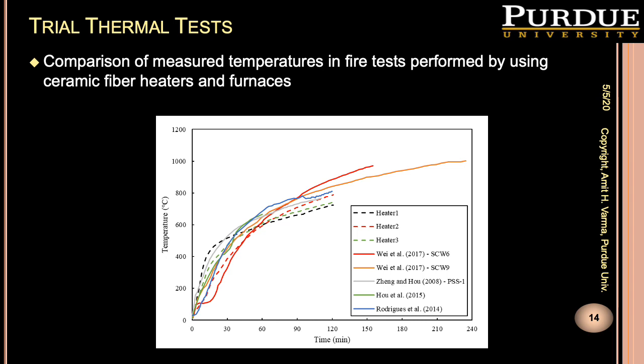I've also added a few lines from furnace tests conducted and available in the literature by different researchers. What all these plots show is that the typical temperature versus time curve that we obtain by using the ceramic fiber radiant heaters is quite comparable to the surface temperature time curves that one would obtain in a full furnace test, in a gas furnace test, as shown here from the various other researchers.